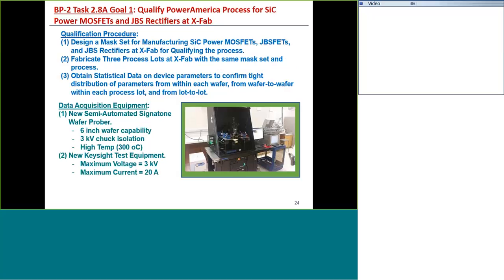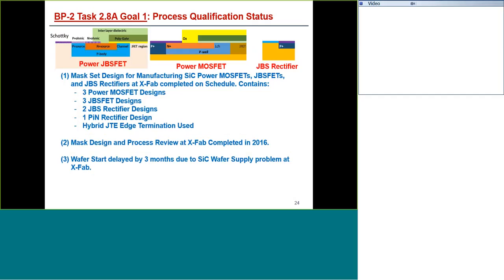In order to take the statistical data, we have just acquired some equipment, a semi-automated Signatone wafer prober with 6-inch capability. It has the capability to test to 3 kV and up to 300 degrees C. And we have purchased a Keysight test equipment set that can measure up to 3 kV at 20 amperes. And this has all been installed and is now operational at CSU.